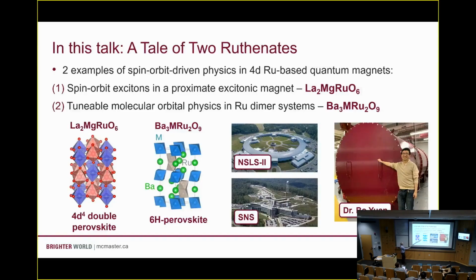And in the other case, we've got this ruthenium cluster magnet, which has these ruthenium dimers. This is going to give us an interesting model system that we can play around with to learn more about molecular orbital physics. And I'll show you a little bit of synchrotron data, resonant inelastic X-ray scattering measurements that were collected at NSLS-II, as well as some neutron spectroscopy measurements from the Spallation Neutron Source.